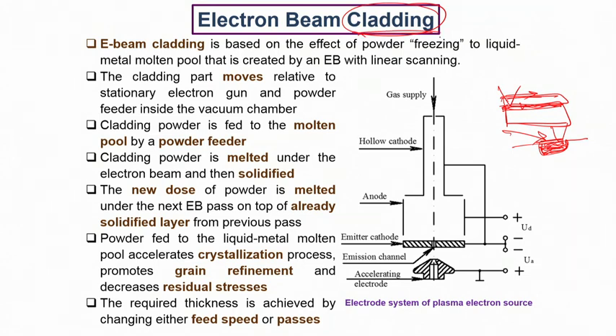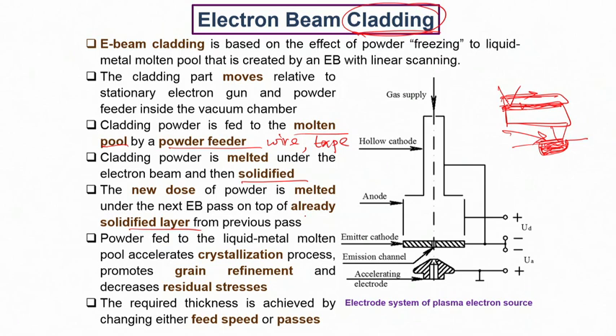It is not only about hardening the layer — if a particular component has developed a crack or dent, you can refurbish or reclaim it by putting material there. This precise filling of the crack or gap is possible by feeding a filler wire, filling the gap with powder, and then using the electron beam to cover that area. When it melts, if the composition is the same as the substrate, the interfaces are practically invisible — they integrate very well with the component. Material can be fed into the molten pool as powder, wire, tape, or other forms. The molten layer solidifies creating a good metallurgical bond, done in vacuum with very high precision.